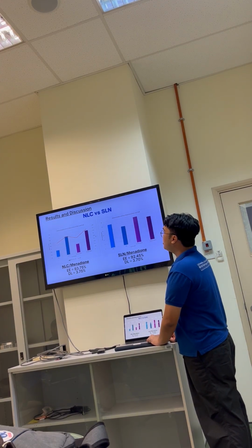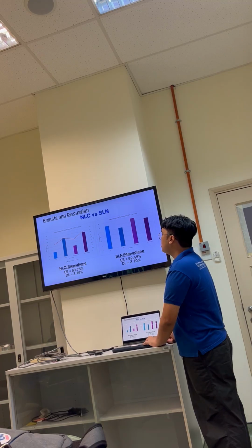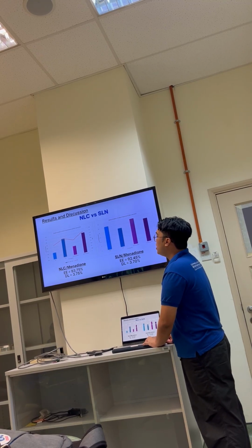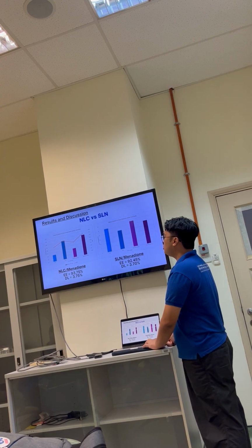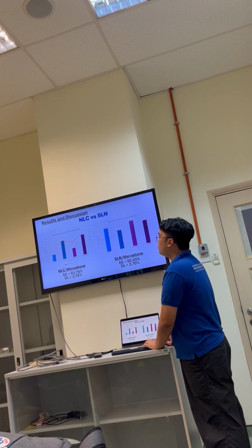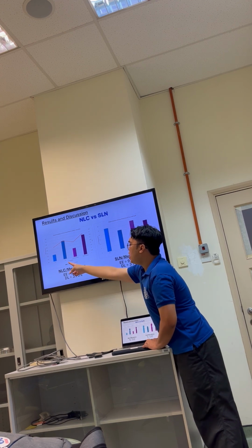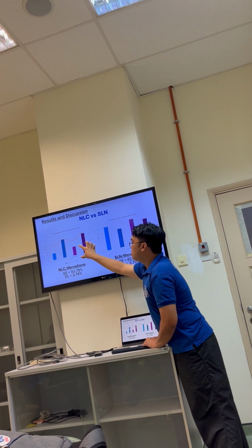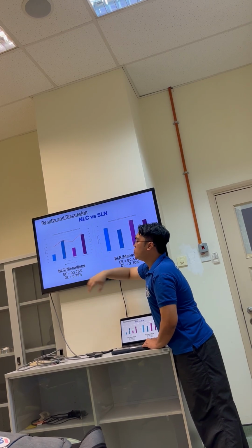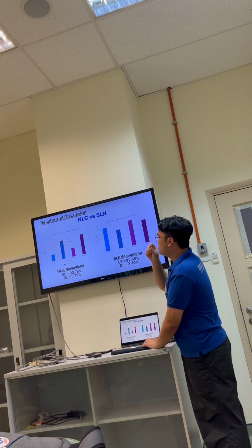I have mentioned earlier that SLN does not contain any liquid component. And we can see here that it likely also has an effect on the mean size and the PDI as well as the zeta potential. I want to invite your attention here because it is very clear that adding the drug to the system would increase the size slightly, which is of course expected because you're adding more stuff inside the particles.